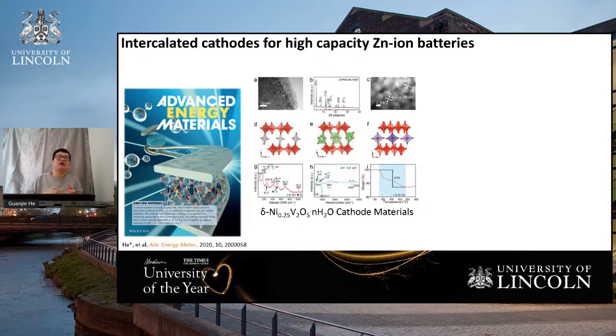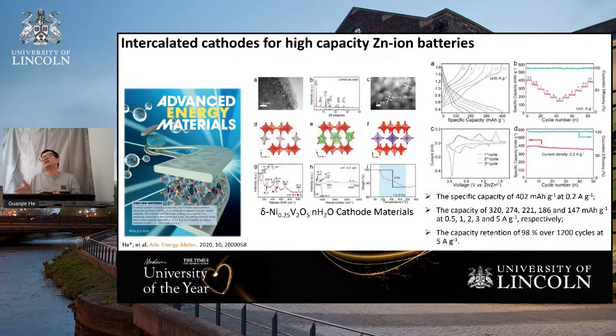And we also did a lot of experiments related to the electrochemical performance evaluation and the materials characterization to find out the suitable pre-intercalated ions. And we find out this phase, delta nickel 0.25, V2O5 can work as a stable cathode host. And the stability is quite high. The capacity retention is over 98% over the 1,200 cycles charge and discharge. So that means we charge and discharge the batteries continuously for over 1,200 times. And the specific capacity is quite good. That is over 400. That's a low current density, 0.2 amps per gram.